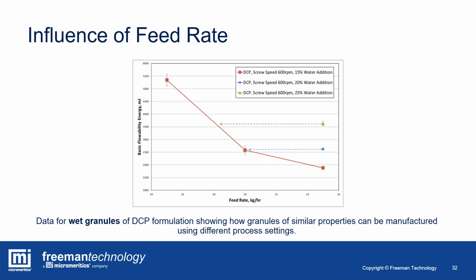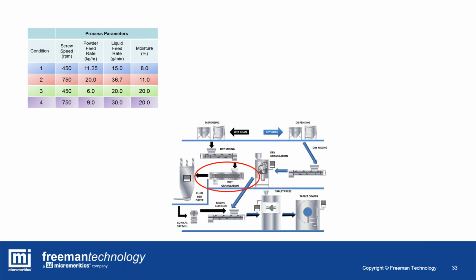And so we took this study further with one of the APIs, and we designed 4 conditions or 4 configurations. You can see here in this table on the left-hand side, and they are all variables associated with the wet granulation process. We had fundamentally 2 different speeds, 450 and 750 were chosen, and you can see on the right-hand column the moisture content that we chose as our set points. We've got 2 relatively low moisture contents, 8% and 11%, and we've got 2 higher ones at 20%. And so what we did is we made granules following these process parameter set points, and we measured their attributes at each stage through the process.